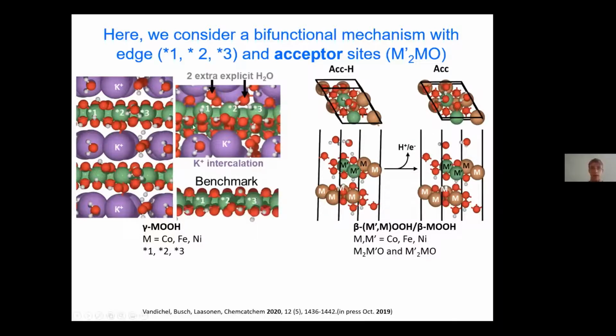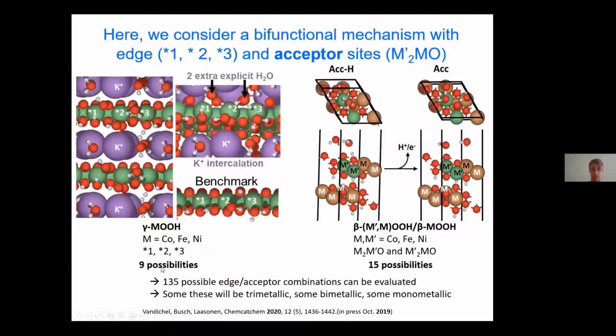But then if we combine this edge with this type of acceptor system, we have something like three different active sites that we have here for three different metal sites. So that can be pure cobalt, pure iron, or pure nickel metal oxyhydroxide. And then three different active sites for each of the pure system that we can combine with a whole series of different acceptor sites that are bimetallic in nature. So we can do a screening study between both these edge sites and these acceptor sites. So then we get a lot of combinations in our study.